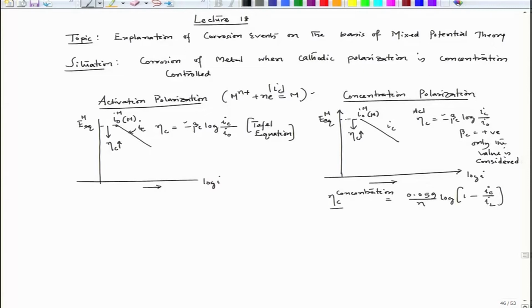So, I can say that this is activation controlled, and this is also activation, but once we go to a very high current density, it will take a flat dip. This point becomes I L, and I L can be expressed as n F D C0 divided by delta, where D is the diffusivity of the ionic species in that electrolyte, n is the number of electrons participating in this reaction, F is 1 Faraday, C0 is the bulk composition of that metal ion, and delta is the boundary layer thickness or the diffusion layer thickness.